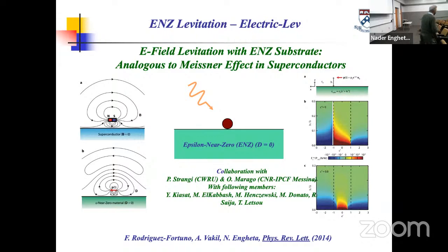We just submitted another theory manuscript to study the effect of the size of the particle with respect to the background. So we'll see what happens. If indeed we show experimentally that this can help to levitate the particle, this could be quite interesting, because if we can levitate this micron size or maybe nano size particle there, then it would not have any friction, and then we can move it over the substrate.